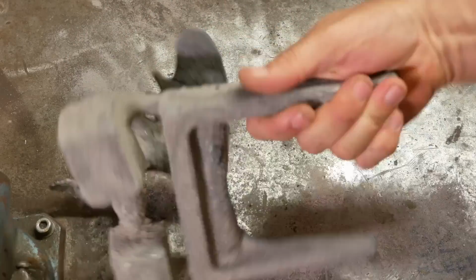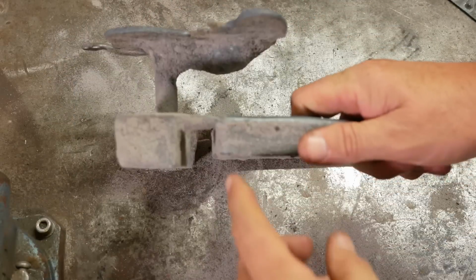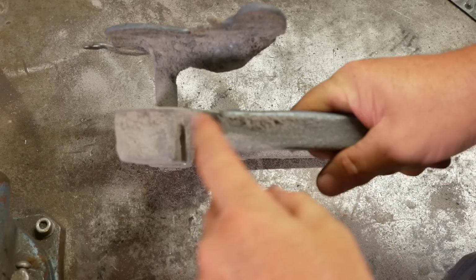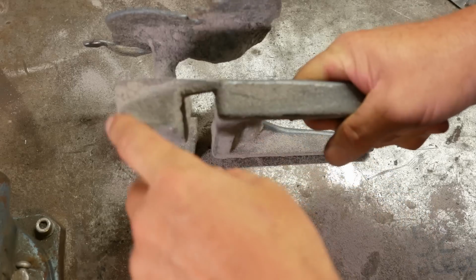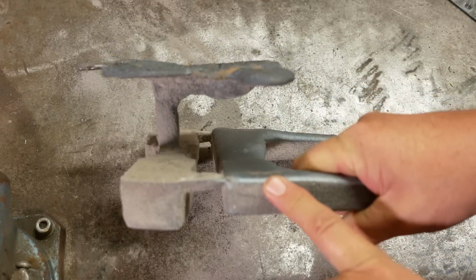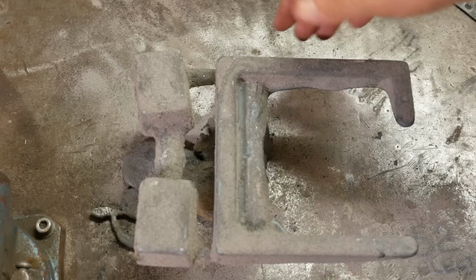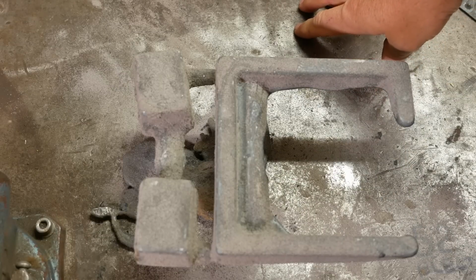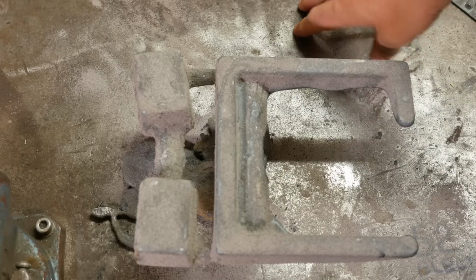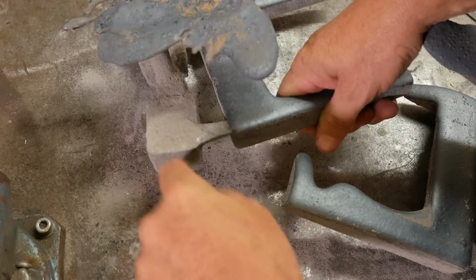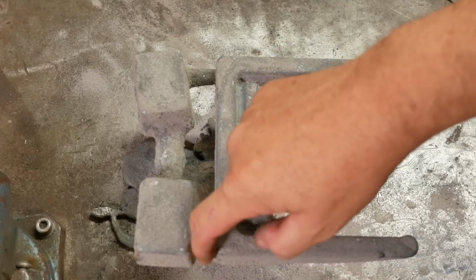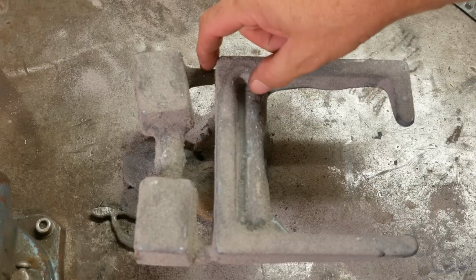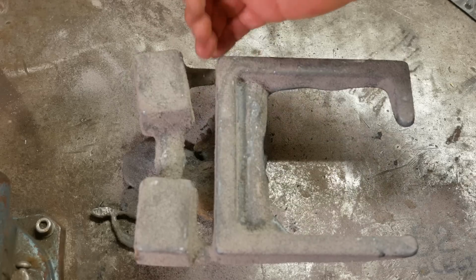The second issue was that I made these connections to the shrink bobs far too small. That's not enough to feed the casting as it freezes. I saw while pouring there were some chunks in it, so I didn't get my metal that clean. The shrink bobs were in the drag, which is the bottom. It may well be that I got some inclusion in each of these runners, which then closed them off.